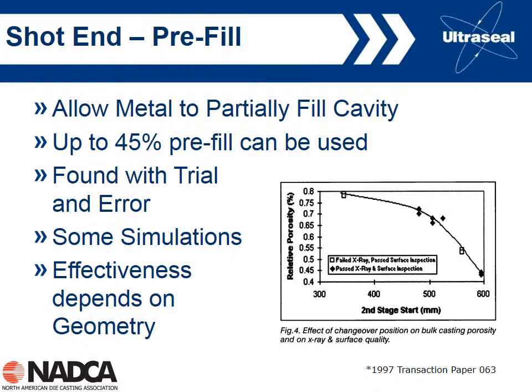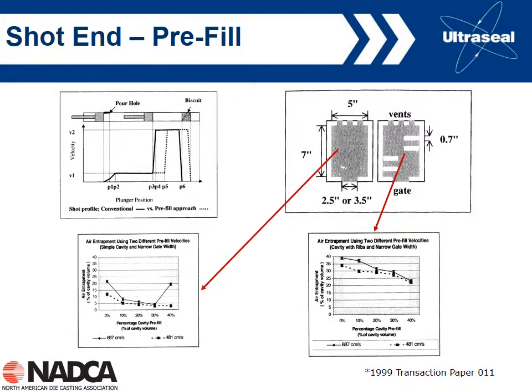However, it does depend upon the geometry of the casting, and that's shown here in this series of graphs. This is again good data from a 1999 paper from the transactions, the effect of pre-fill. What they did is they looked at two different die cavities, or they modified their die cavity. Here we have a simple plate where we're gating it here with vents on the end, and then they put baffles in the die to have a more tortuous path in terms of actually filling the part. And so they looked at the effect of pre-fill for the two different dies based on different slow shot velocities. For the simple plate die, the data is shown here on the bottom left, where again we're looking at air entrapment against percentage of cavity pre-fill for two different slow shot velocities.